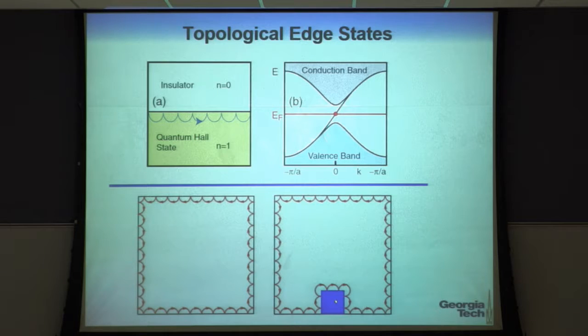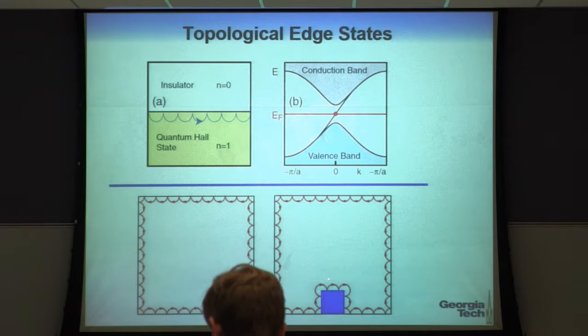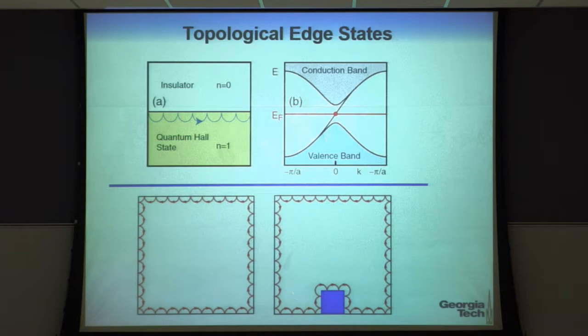And if I put some disorder at the edge, in fact, it doesn't make any difference. In order for this electron to turn around and go the other way, to scatter and introduce resistance, what it would have to do is actually go all the way across this material. Okay? So the edge state propagating this way, in order to turn around, to be backscattered, it has to go all the way across the material. And that is incredibly improbable. And that's why the resistance, the longitudinal resistance in this state actually goes to 0. So this becomes a dissipationless state.